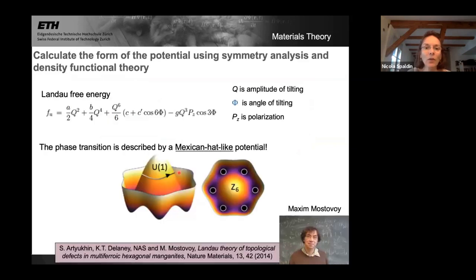So one can also, instead of just thinking about where the atoms move to, be a bit more formal and work out the form of the potential describing that transition using symmetry analysis, and then one can calculate the detailed potential surface using density functional theory. This was work that we did in collaboration with Maxim Mostovoy and his group, and the free energy describing the phase transition in the hexagonal manganites looks like this. I don't want to go through it in detail, but to point out that Q here, which is the primary order parameter for the transition, is the amplitude of the tilting. It's how much those polyhedra have tilted.